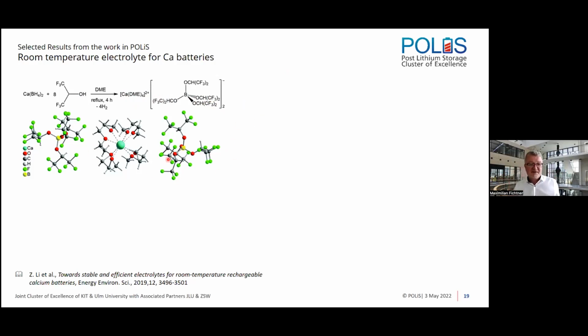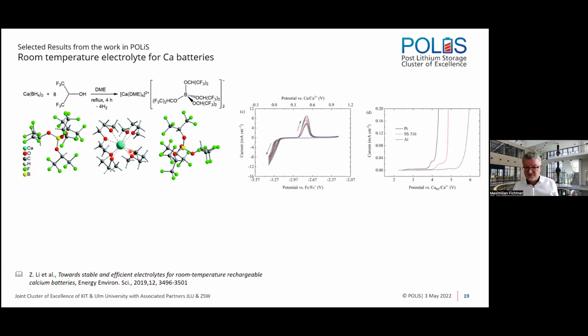And this is a single crystal image from the product that you get. You see here the calcium, coordinated by solvent molecules, DME in that case. And here you have this hexafluoroisopropanolate boro complex. So this is the boron with 4 of these isopropanolate complexes. This looks a little bit like a hedgehog, where you have the fluorines outside, and they don't want to get in contact with anything. They leave the magnesium or the calcium alone here.